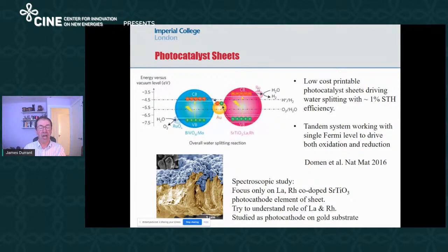It's just light. And these systems, because it's working as one unit, have to work with a single Fermi level. So the Fermi level in the system needs to be the same for both the oxidizing system and the reducing system. And that's been puzzling us. And we wanted to understand that. And in particular, we wanted to understand why you have to co-dope strontium titanate with both lanthanum and rhodium to make it work. And so we did a study spectroscopically looking at this lanthanum and rhodium doped strontium titanate deposited, as you can see, as a rather disordered photocathode on a gold substrate.